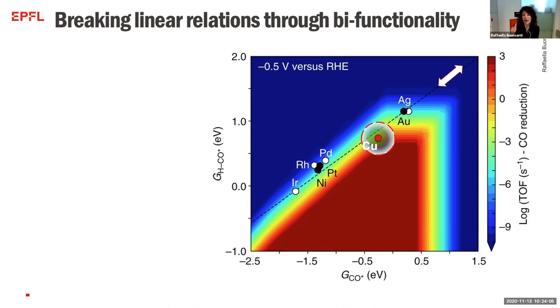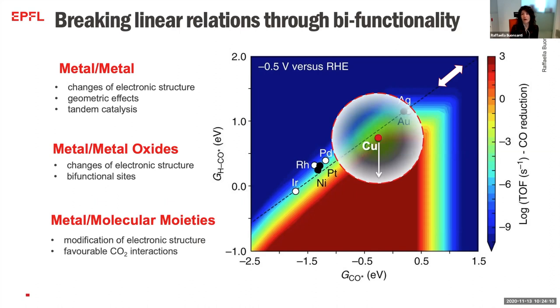So in order to break what are called scaling relationships, we really need to start to mix copper with different materials. And the problem is that we still don't have input from theorists because we don't really have a reaction mechanism. So what we have been doing in the group is utilizing a bit of our chemical intuition and our materials chemistry in order to start testing some hypotheses and trying to understand how interfacing copper with different components might change the selectivity in CO2 reduction.